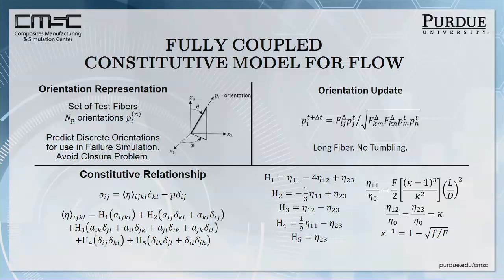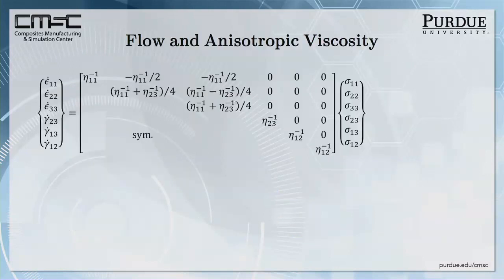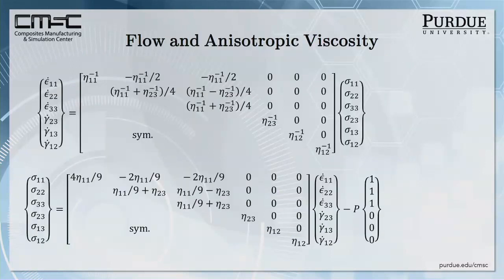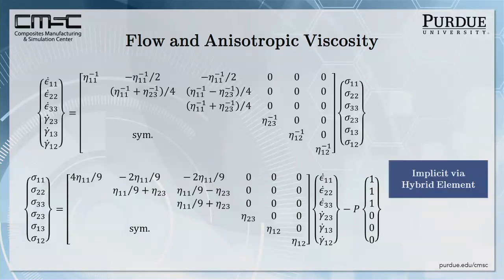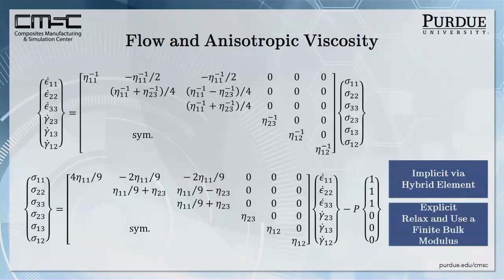It turns out these other two are pretty much the viscosity of the polymer with a small geometric change in it. But by the way, those differ by sometimes as much as a factor of a million. So that puts that in perspective. Once you've got that relationship, you can build a stress-strain rate relationship, and you can use a conventional solid mechanics finite element model. We used ABAQUS in this case, and build with this methodology.